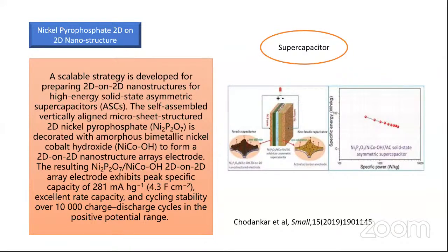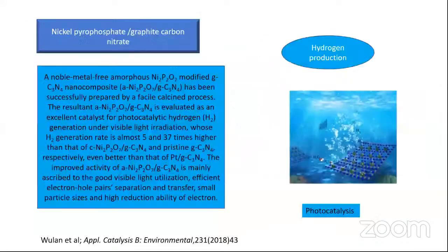Nickel pyrophosphate graphitic carbon nitride, again a novel material for hydrogen production, because we had seen in earlier slides oxygen generation, but equally hydrogen generation is also required, and that is done by water splitting. So novel metal-free amorphous nickel pyrophosphate modified graphitic carbon nitride nanocomposite have been successfully prepared by facile processes. And this gives very, very important hydrogen generation.